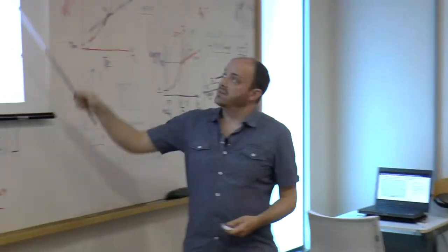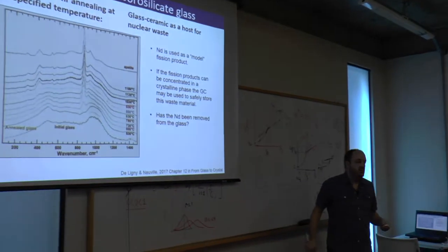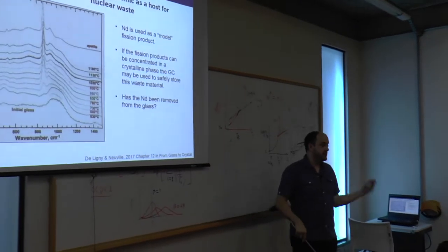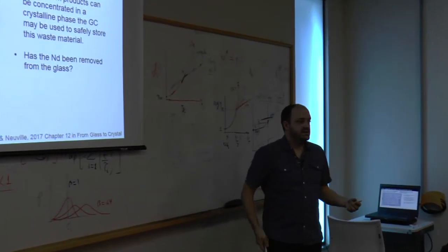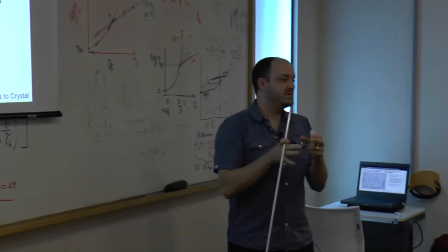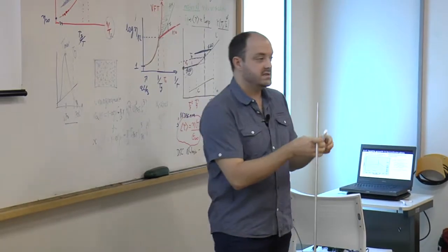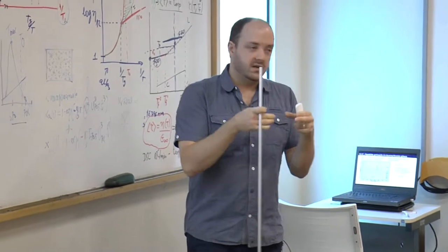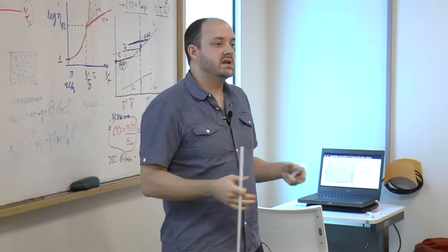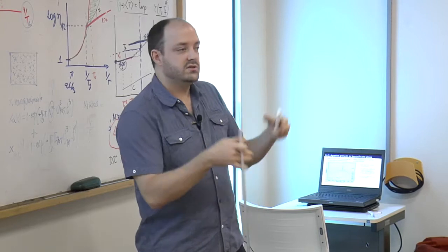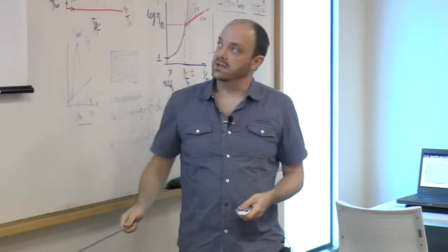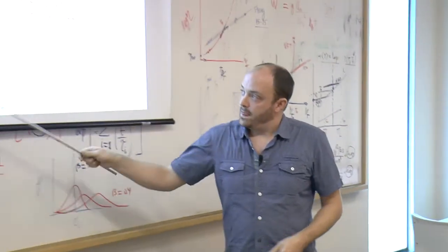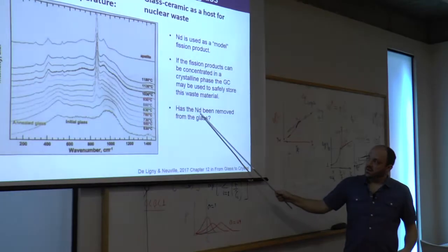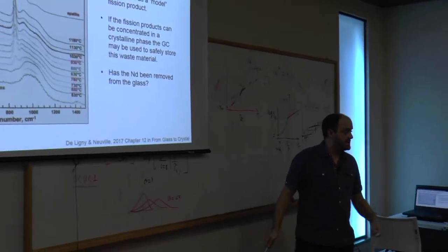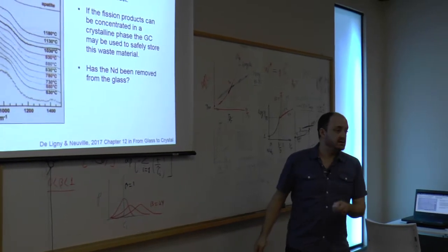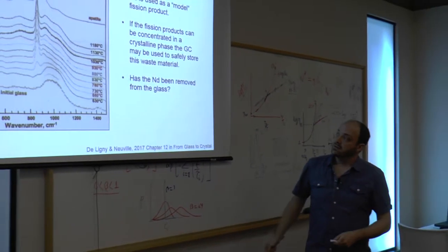And the neodymium that they added, a small amount, was used to mimic the fission products from the reactor. The idea was that if we can separate these fission products into the mineral phase, into the crystal phase, then we can isolate them from the glass matrix, and they'll be more stable than just storing them in a glass in the original case. So their question ultimately was: was the neodymium actually removed from the glass, and was it stored in these apatite crystals that are grown in their glass ceramic?